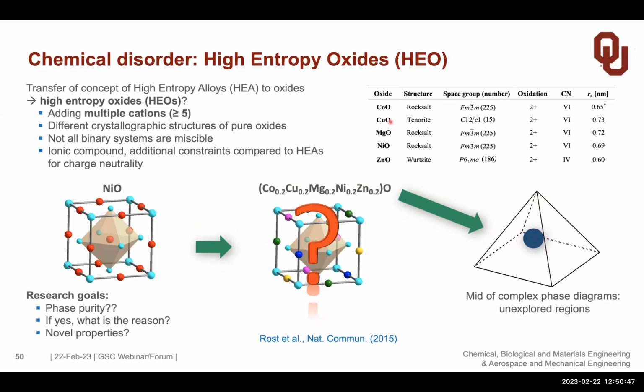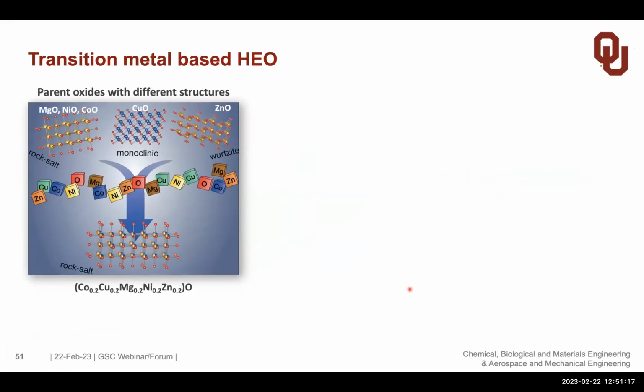And interestingly enough, you take the different oxides which you put together, they have different structures, but at the end, as we found, we find a rock salt structure. So the other ones kind of are forced into a rock salt structure, even though they don't like it if they are alone. In addition, some of these binary systems are not miscible. They form different phases and so on. But at the end, it's the high entropy which brings the different materials together in a simple rock salt structure.